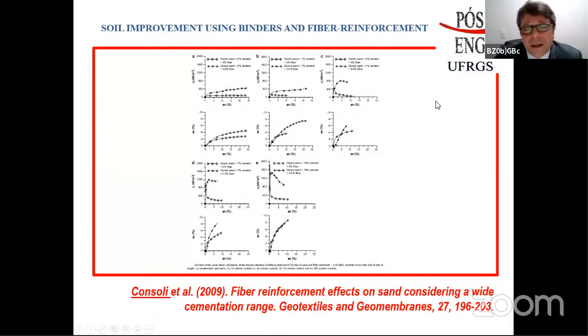Okay, so if you put some cement and also some fiber, depending on the amounts that you have, you might get results like this one. You have 0% of fiber and 4% of cement. You have a behavior that is quite stiff and then brittle, and then it comes down to a softening. But if you add 0.5% of fiber, besides increasing the strength due to the fiber insertion, you also have a ductile kind of behavior. So you can try to find optimum amounts of fibers and cement in which you increase stiffness, increase strength, and also keep a ductile behavior, which is quite interesting. Such a result was published in 2009 in Geotextiles and Geomembranes.